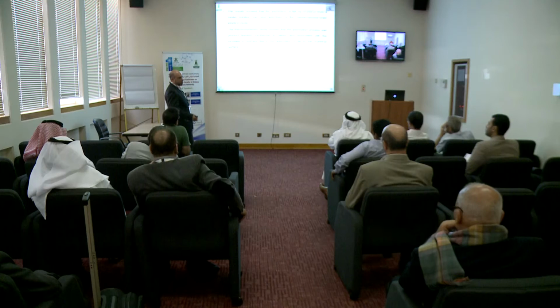Surface area is around 700 square meter per gram for the removal of different organic pollutants from the environment. From the kinetic point of view, it follows the pseudo second order. Again, thermodynamics of this one, it's exothermic, which is the most favored one. Exothermic means it requires less energy, less heat to remove the organic pollutant from the environment compared with the manganese oxide. And we found the efficiency of the removal is very high compared with other things.